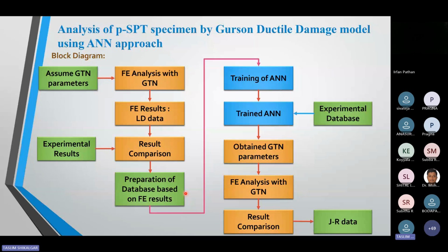I want to tell about the artificial neural network approach, how we can utilize this ANN approach to get the ductile damage parameters. So initially, I assumed some ductile Gurson parameters, just randomly: 9 parameters, of which 6 I fixed. I varied only 3 parameters. I will tell more about it in the next slide, which 3 parameters I varied. I performed many numerical analyses with these Gurson parameters. To perform this type of simulation with a damage mechanics model, I need approximately 20 to 30 hours for one simulation.